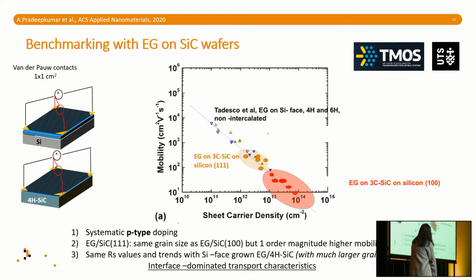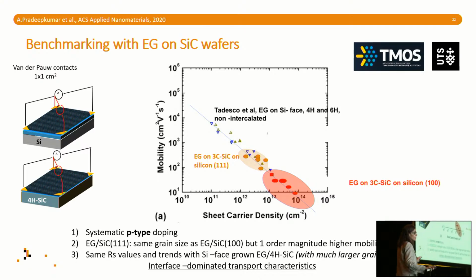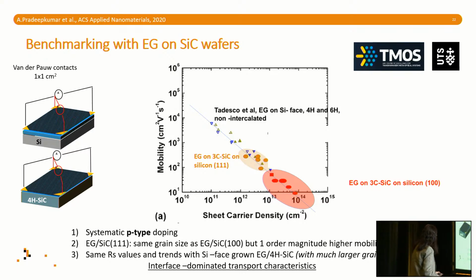Which is surprising in hindsight because this was a completely independent work, but not surprising because we're talking about graphene. So that confirms that we're talking about graphene, basically. This is really important also because graphene, as you know, doesn't have doping per se unless you do something specific. But graphene is basically dependent on charge transfer doping. And the charge transfer typically happens at the interface. So basically what's happening here is that we are interface dominated, not grain size dominated, in terms of conductivity, not in terms of mobility, which is really important to know.